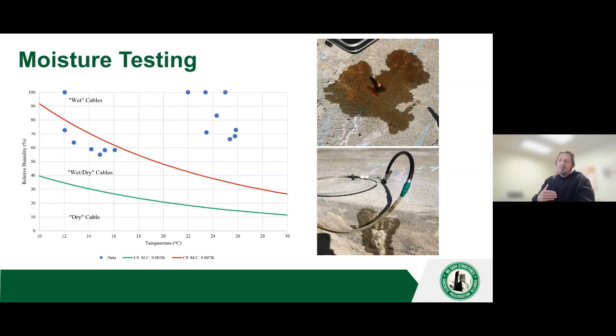So again, we're looking at probabilities, not unlike the half-cell corrosion potential testing, right? We want to know where our wet cables, our wet dry cables, and so forth are. So if we've got water inside of the cables, we're going to know. If we've got 100% humidity, there's ponding water in those strands, which means that there's a high likelihood that active corrosion is going on, especially if there's an inclusion of chloride.